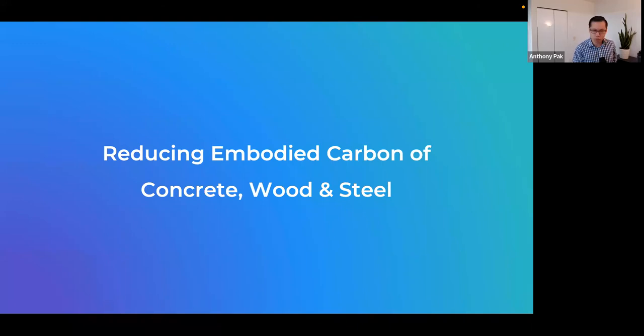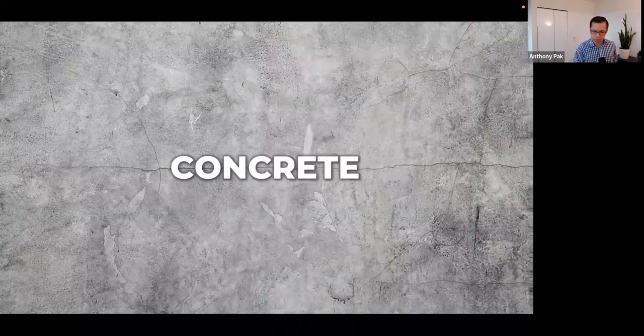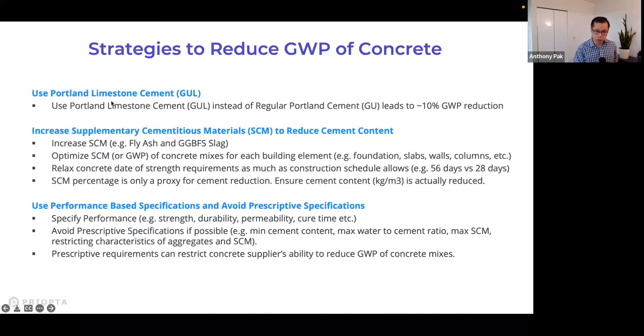Okay, so now I'm going to get into some of the strategies for how you reduce embodied carbon. So for example, with concrete, this oftentimes is one of the most significant materials from an embodied carbon perspective. So what can you do? First, the low-hanging fruit is to push for using Portland limestone cement instead of regular Portland cement, or GUL versus GU. So if you replace the typical regular Portland cement with GUL, Portland limestone cement, that roughly leads to about a 10% reduction in the global warming potential per meter cubed of concrete. And generally, there's not too much of a performance hit or even a cost premium per se associated with this. So this is something to push for on your projects.